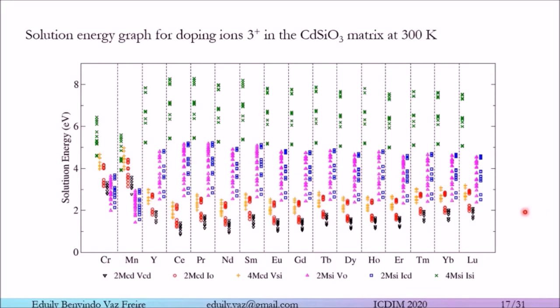Okay, next graph. This graph shows the solution energy for extrinsic defects in the CdSiO3 matrix at 300 Kelvin for all dopants with valence 3+. We observed that it followed the same trend for rare earth dopants and for transition metal dopants.